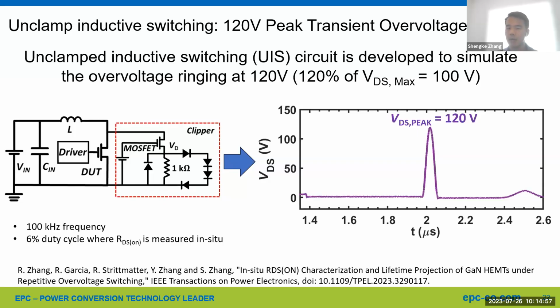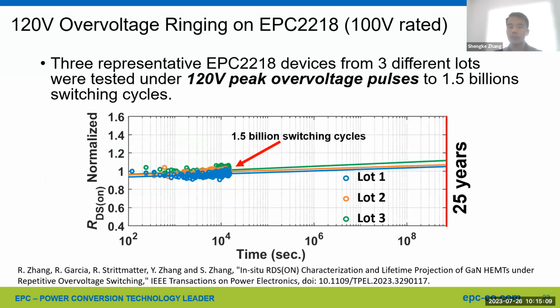So now let's examine how well our GaN FETs performed on the repetitive 120 volt over voltage testing. So here are the test results. We tested 3 representative EPC2218 100-volt rated GaN FETs from 3 different lots and wafers to 1.5 billion 120 volt over voltage spikes, where very minimal RDS(on) shift was observed. When we project the shift to 25 years using the lifetime model we developed using the hot carrier trapping effect, we observed that all the data points collected by the UIS, the unclamped inductive switching circuit, fall exactly on the projected line, and the projected shift for 25 years is less than 10%.